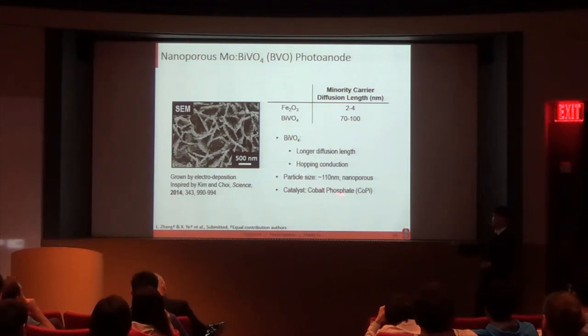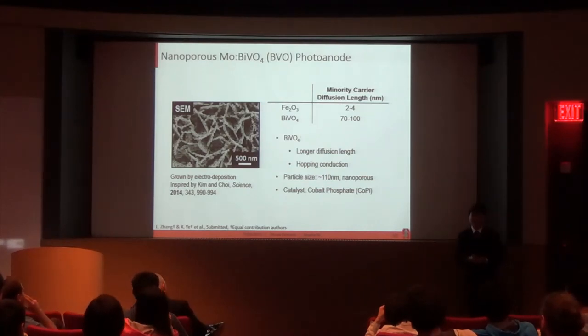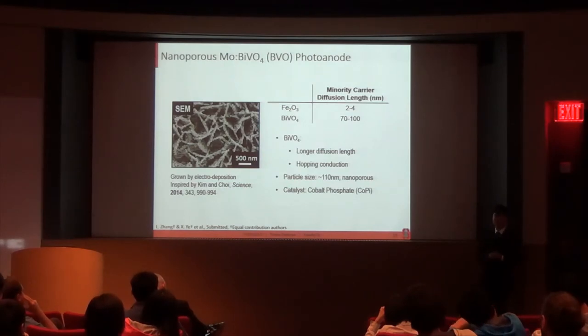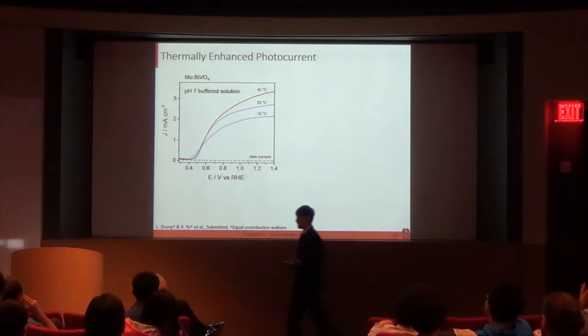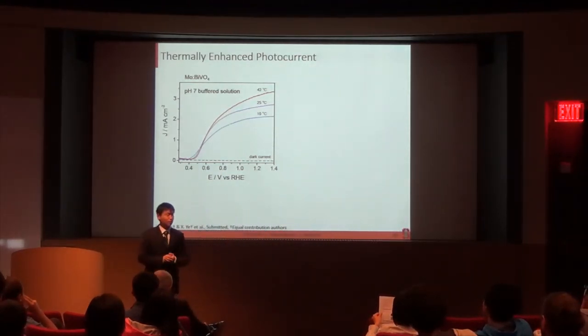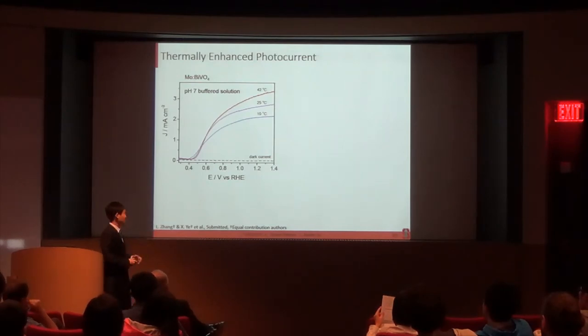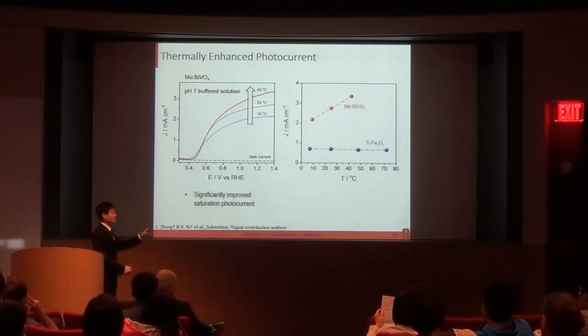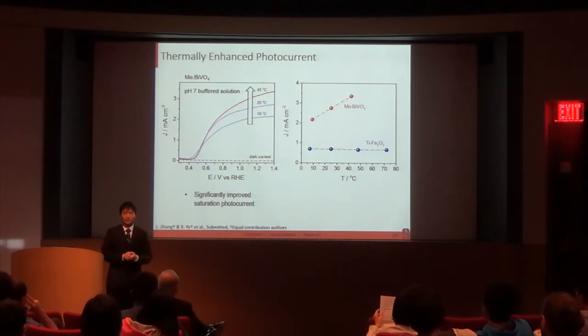We also added a cobalt phosphate, or Co-Pi, catalyst on top of this photoanode to improve the reaction kinetics while suppressing the surface recombination. So before I go into more mechanistic analysis, let me show you this final result for temperature-dependent photocurrent. Just by slightly increasing the temperature from 10 to 42 degrees Celsius, we see a more than 150% increase in photocurrent. And such an increase is much more significant as we compare to the hematite photoanode.